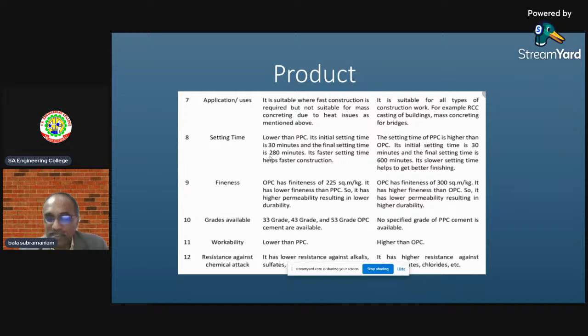The fineness also differs because the basic material inside also has some changes, right? We have OPC and fly ash here. For pure OPC it is 225 square meters per kg, whereas for PPC it is 300. PPC is a little finer. And the grades available for OPC are 33 grade, 43 grade, 53 grade. You take any cement bag, it will have a grade on it. Whereas in PPC, in any blended cement, there is no grade provided by IS. Blended cement is blended cement. The workability of OPC is much lower than PPC, whereas PPC is much higher. And OPC has, as I told you, chemical resistance against chemical attack. It is a little lower in resistance, and PPC is a little higher.